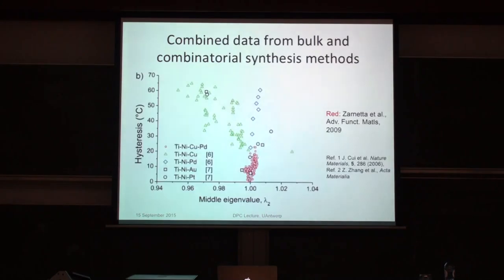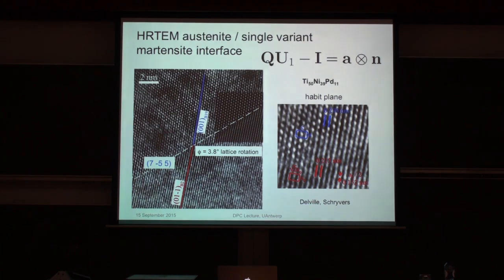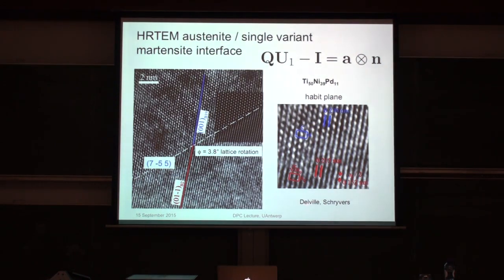So, of course, all that was done, but we didn't know if the theoretical explanation had anything to do with this graph, because we had never seen one of these interfaces. So, of course, we come to Antwerp, and this is some nice work from Remy Delville, a former student of this department, and he managed, in a material which was near satisfying lambda 2 equals 1, I'll talk about that in a minute, we used to think this was the material at lambda 2 equals 1, and it had about 6 degrees hysteresis.